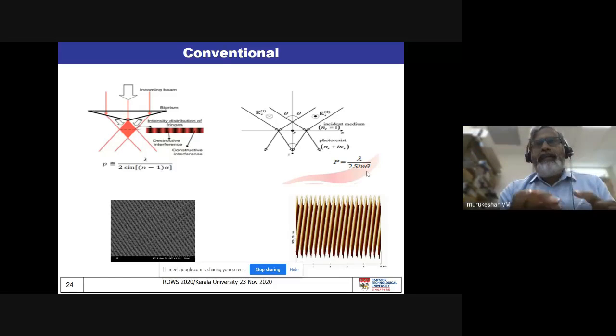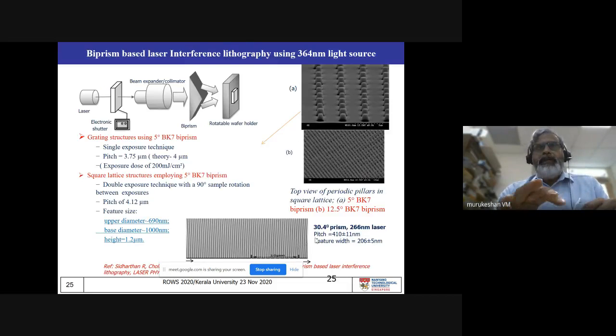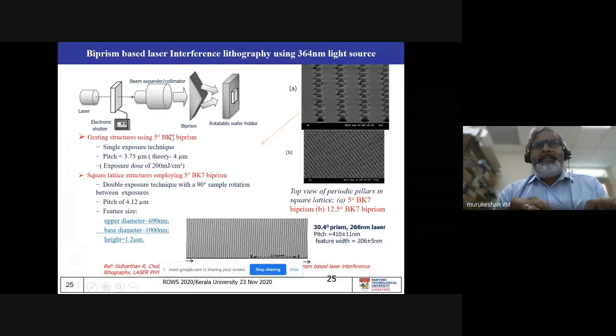If you are doing that, you normally get straight line patterns, which you can imprint on a photosensitive substrate. Then you can transfer them into a semiconductor wafer. And that is what we are going to do here. Let us see what happens. When we use this very simple biprism-based configuration, using the normal glass prism, a BK7 biprism, okay? By controlling the prism angle, we can get very nice line features.